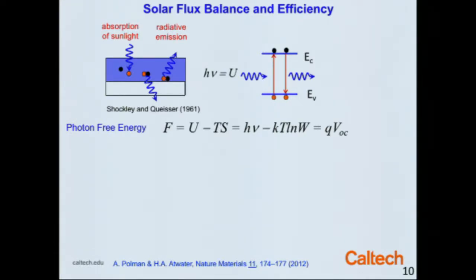We can think about this on an energy or enthalpy basis because we have a level diagram. We have a ground state and an excited state, a valence band or a conduction band, and we're photoexciting carriers from the filled states to the empty states in a semiconductor. So there's a clear diagrammatic basis for the absorption of a photon, excitation of a carrier from the valence band to the conduction band, and the inverse recombination process that leads to carrier radiative emission.